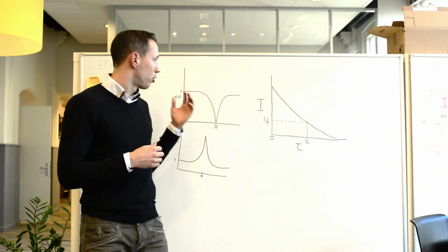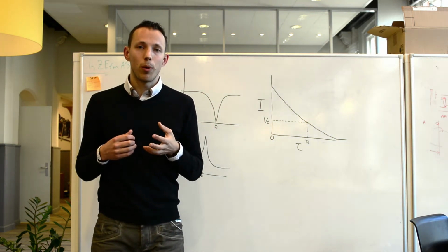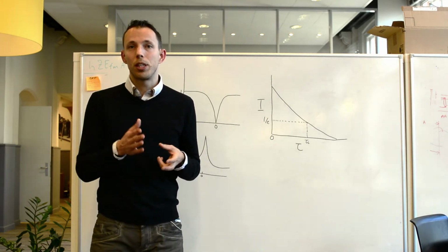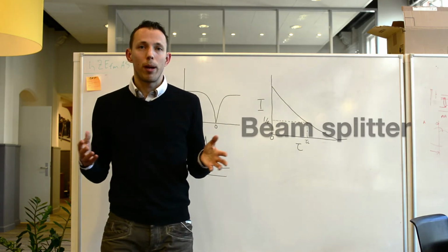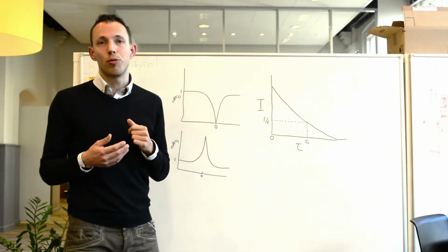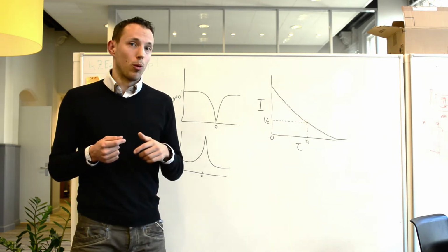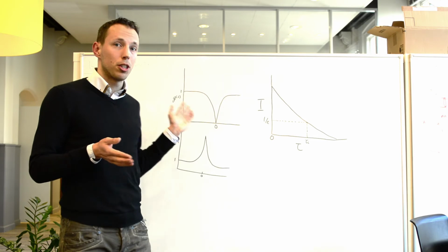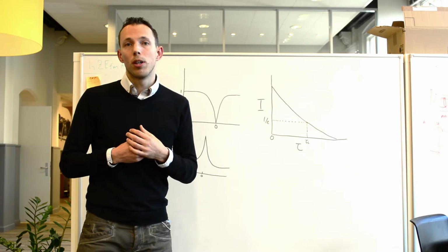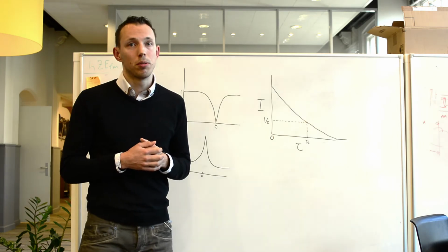For the G2 acquisition, you use a similar approach, where rather than having one single photon detector, you have two, and in between there's a beam splitter. And this is called a Hanbury Brown and Twiss interferometer. And this allows you to measure this G2 function and the probability that you detect two photons simultaneously. One nice thing is that the G2 acquisition you can also do with a continuous beam electron microscope, although it's also possible to use a pulsed electron microscope, which has certain advantages for the signal to noise ratio.